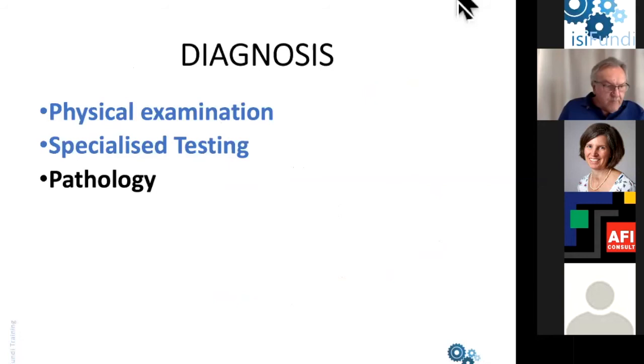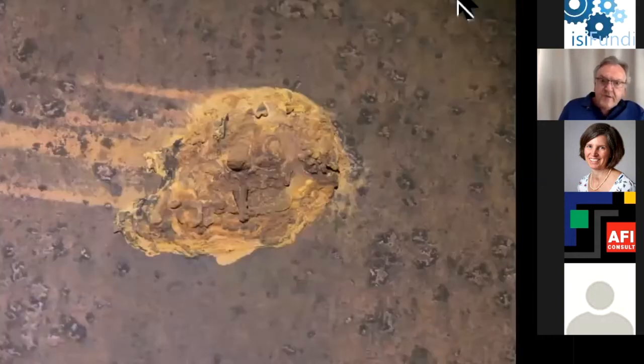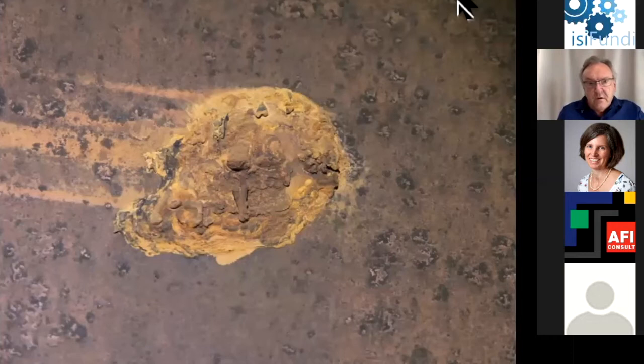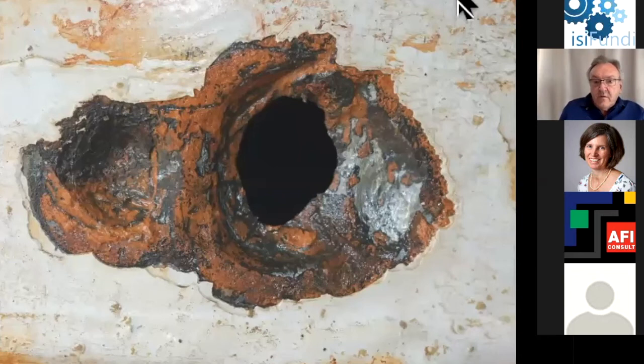Pathology is the investigation of corrosion that has already happened. So, for example, by looking at the type of corrosion product, we can tell whether the corrosion mechanism was bacterial or stray currents or whatever. This particular example is bacterial corrosion with a highly voluminous corrosion product on the surface. And when we remove it, we find that there's the characteristic shiny surface underneath. And you can see that in this particular situation, the pipeline has been perforated by the bacterial corrosion.